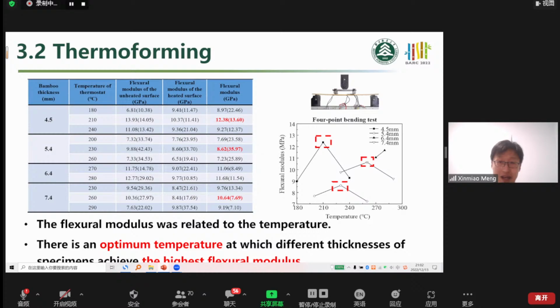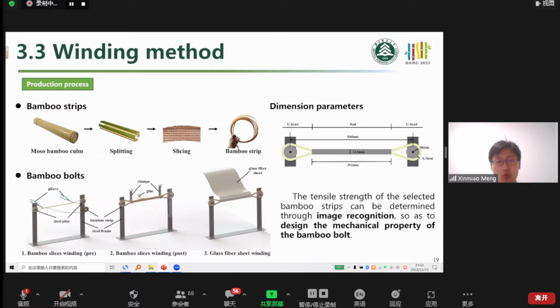We found that the flexural modulus changed with the temperature, but I think more microscopic research should be done to explain the relationship between the modulus and the temperature. We just found the trends, but we didn't find the rule. Then we tried another way to make the U-shape, and it is a winding method. We use the bamboo strips and use winding with FRP to get the FRP bamboo composites.